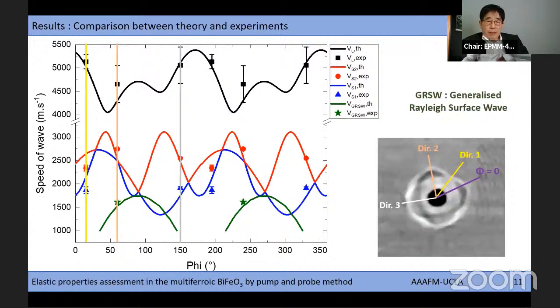One velocity along direction 2 is below the calculated bulk shear velocities. To find an explanation for this apparent discrepancy, we have calculated, with a homemade program, the generalized Rayleigh surface wave for a semi-infinite anisotropic elastic medium. One can see the good agreement between the experimental velocity and the calculated surface acoustic mode, even if this comparison is only based on this unique analyzed experimental point.